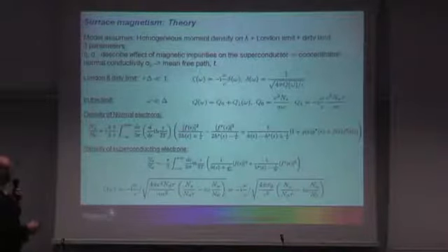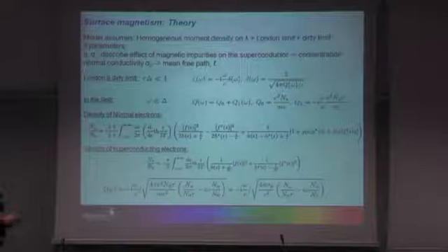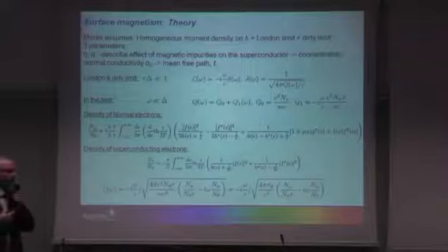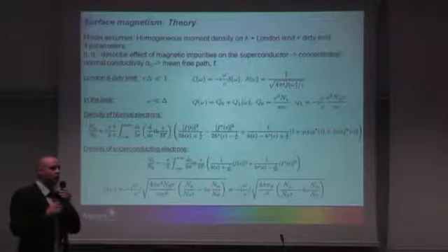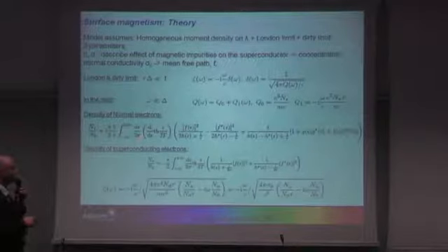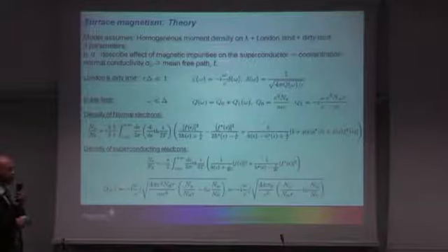This is easier than the inhomogeneous model, where you have just a layer of magnetic impurities, which is closer to reality, but this is just easier to do. And in the dirty limit, we have 3 parameters, and I will come back to explain each of them. The mean free path, the normal mean free path, so diffusion on normal, non-magnetic impurities. And we have eta and alpha, which are 2 parameters describing the effect of magnetic impurities on the superconductor. So we have 2 types of impurities here.